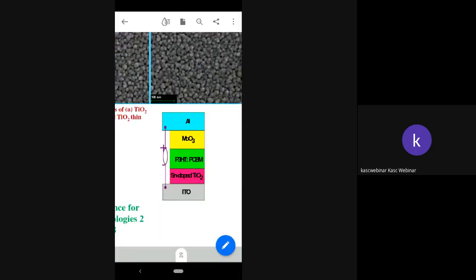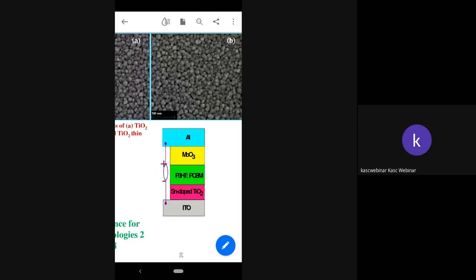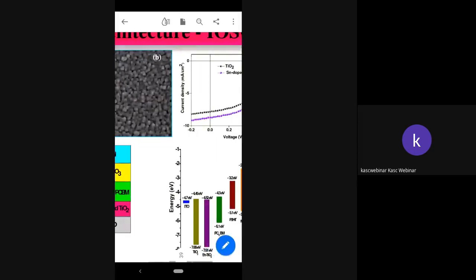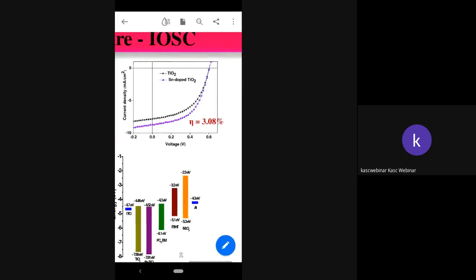Figure A and B shows the surface morphology of TiO2 and tin doped TiO2 thin films, which are prepared by sol-gel spin coating technique. The prepared films are constructed in the form as shown in figure C, which I mentioned earlier. Here, TiO2 acts as electron transport layer, and P3HT:PCBM is used as active layer, and molybdenum oxide is used as hole collecting layer, and aluminum is used for contact. This type of fabrication showed an increased efficiency of 3.08%. You can see the graph that corresponds to JV characteristics of the prepared inverted organic solar cell.